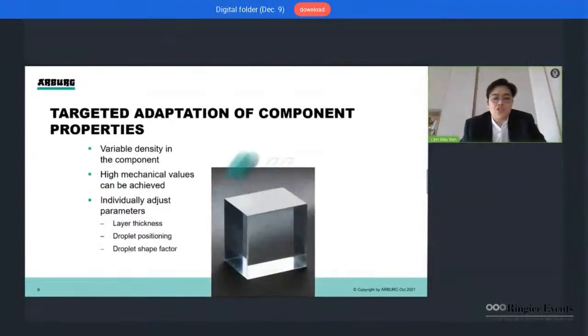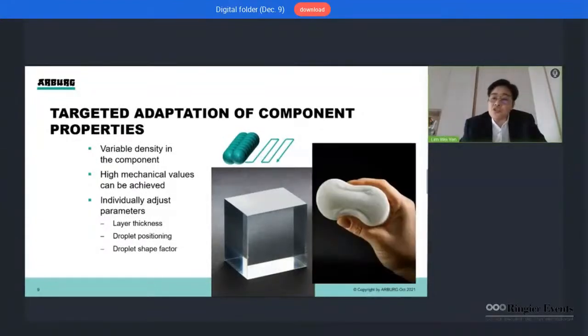We can also place droplets closer together to create a very high density part, which in return gives us very high mechanical strength. This example is a PC cube polished on all sides to show not only the clarity, but especially the density of the part. Vice versa, we are able to space out the droplets and hence reduce the density of the part. In this example on the right, a TPE printed with less density mimics the function of a sponge or filter.